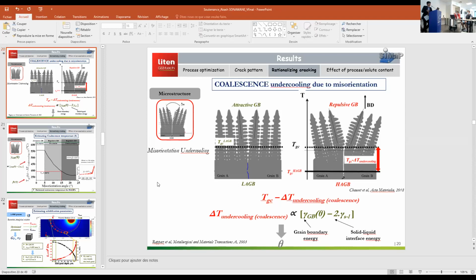But if we identify such elements which show clearly that they can control this particular solid liquid interface energy, we might have better control over the coalescence. I think so, compared to the grain boundary energy, which can change due to the misorientation for sure.